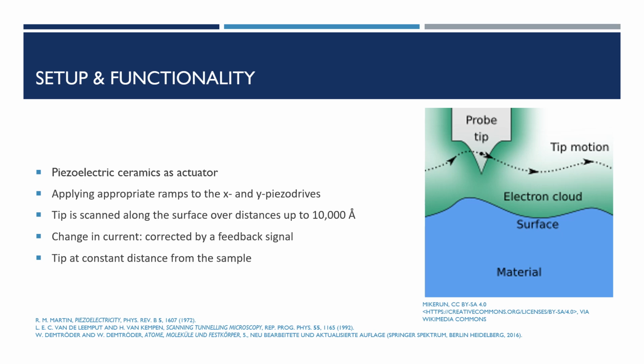This precision of the drive of the tripod is so good that currently only vibration limits the vertical resolution of the sample surface. This resolution is currently in the range of a few hundredths of an angstrom. At the junction, a constant voltage is applied, a few millivolts up to a few volts. A control unit regulates the Z piezo drive in such a way that a preset current, several hundred picoamperes up to several nanoamperes, is established. Any change in current will be corrected by a feedback signal to the piezo drive, which will position the tip at a constant current level above the surface.